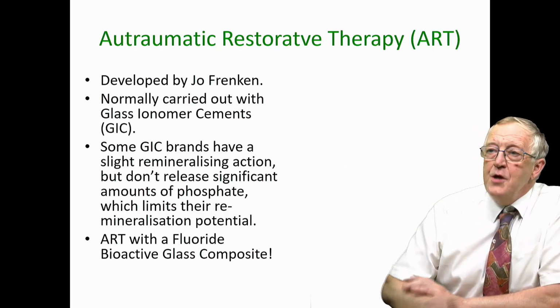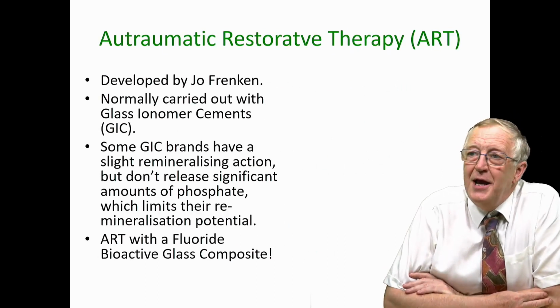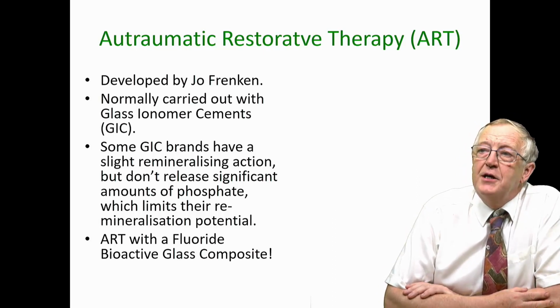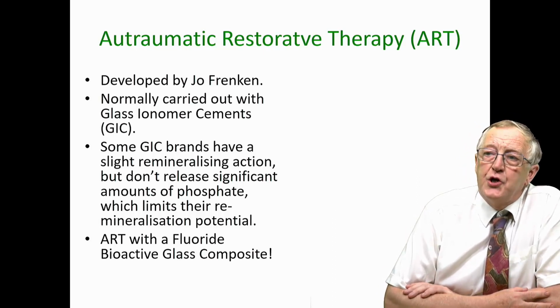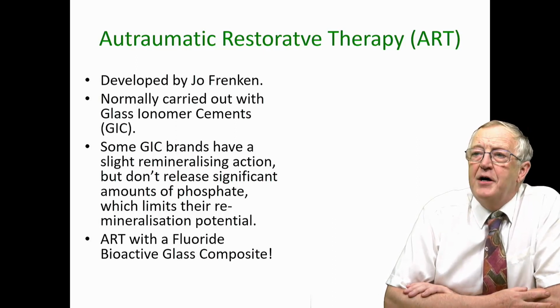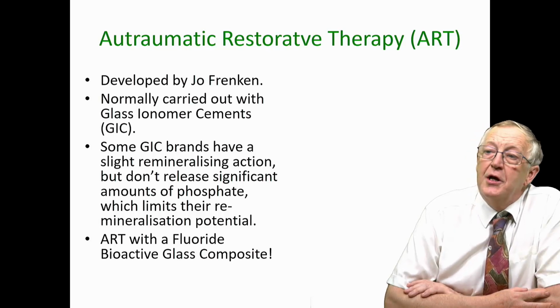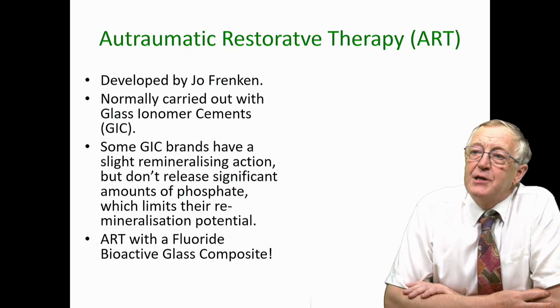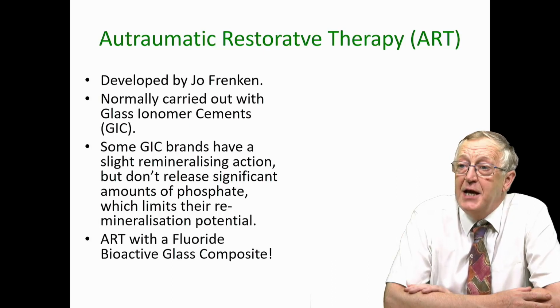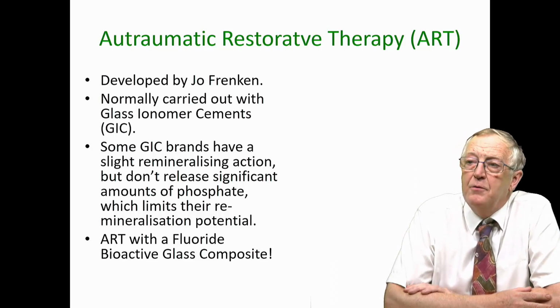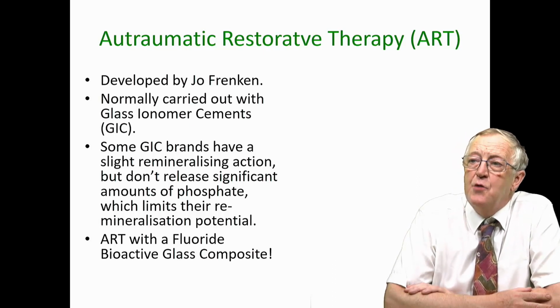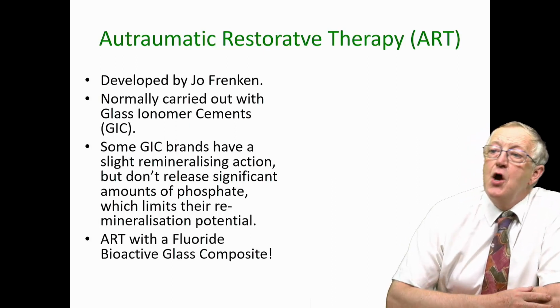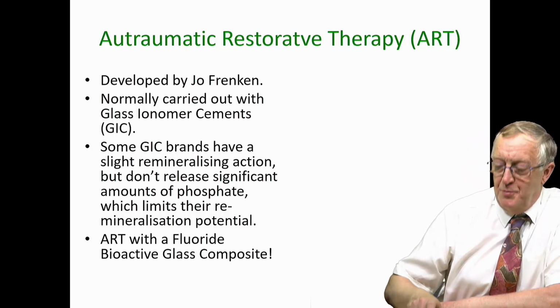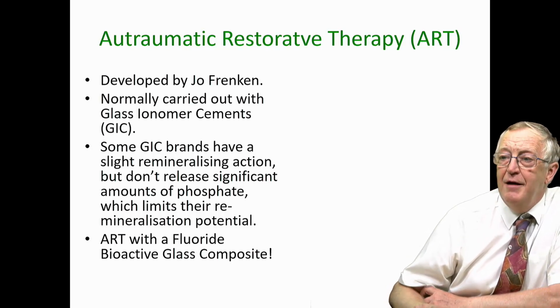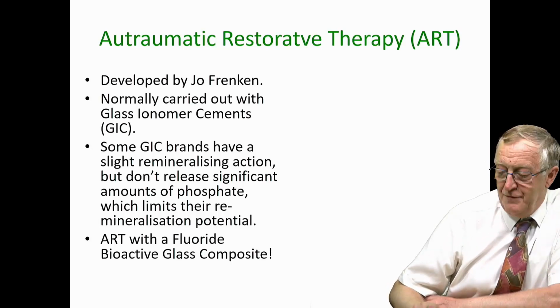So atraumatic restorative therapy was developed by Jo Frencken. It's normally carried out with glass ionomer cements, and some glass ionomer cements have a slight remineralizing action. In other words, they can put back some of the lost mineral from decayed dentine. But one of the problems with glass ionomer cements is they don't release significant amounts of phosphate, which limits their remineralization potential. What we're doing here is ART with a fluoride bioactive glass composite.